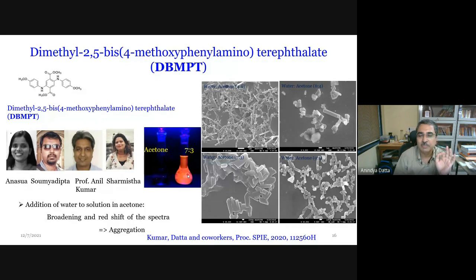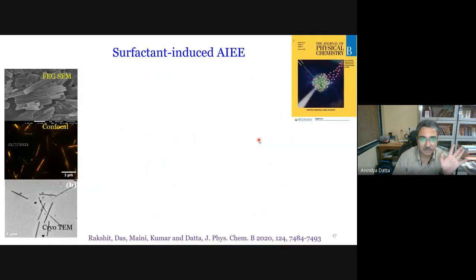But the problem with this solvent mixture experiment, as we found, was that it was very difficult to quantitatively reproduce conditions. So we tried to clean up the system a little bit, no pun intended, by adding surfactants. When we add surfactant to DBMPT in stoichiometric amounts, we are not talking about an experiment with 1 micromolar of the probe and millimolar surfactant. We are talking about a situation where they are present in more or less the same quantities. Then we get these nice, good looking nanorods, which one can see not only under an electron microscope but also under a confocal microscope. We were a little worried that perhaps these nanorods come out only when you remove the solution, but then we saw them in cryo-TEM as well.